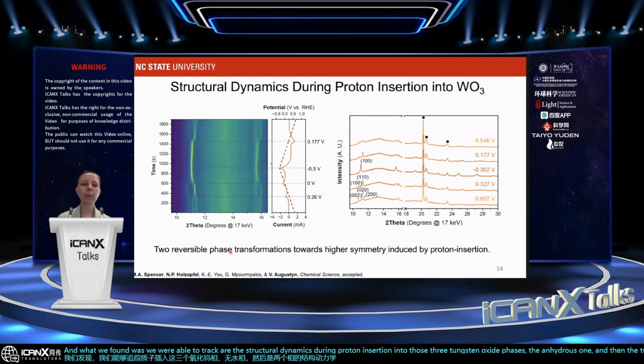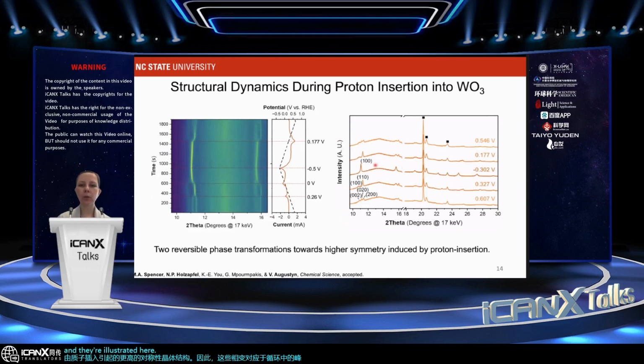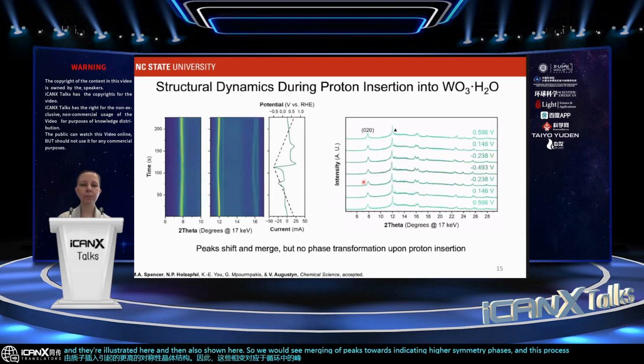And what we observed from these operando X-ray studies is that in the case of the material that had no water, there were 2 reversible phase transformations where the material was going towards a higher symmetry crystallographic structure induced by the proton insertion. So these phase transitions corresponded to peaks in the cyclic voltammograms. And they're illustrated here and then also shown here. So we would see merging of peaks, indicating higher symmetry phases, and this process was reversible.